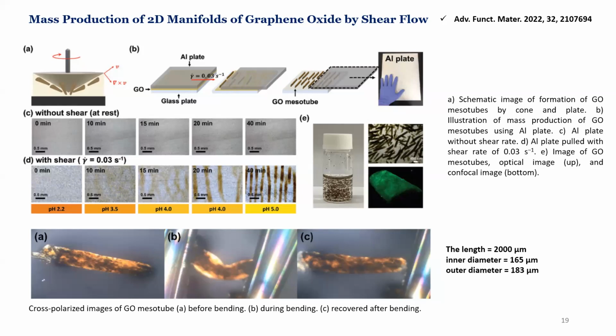Two glass plates were taken. One of them was fixed on the bench. The other one was covered with aluminum foil, scrubbed with metal scrubber. A specific amount of graphene dispersion was put on the fixed plate. The pH was 2.2. We observed that if the pH goes above 3, we cannot obtain these mesotubes. So we kept it at 2.2. The upper glass was slid slowly at a specific rate, which applied the shear, and mesotubes were formed after 40 minutes.